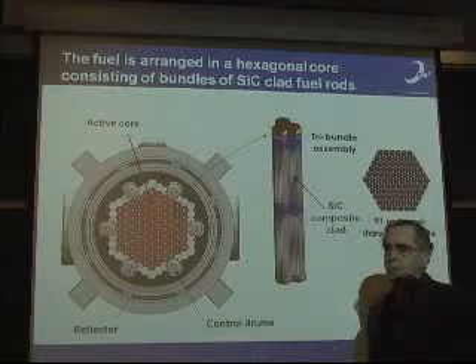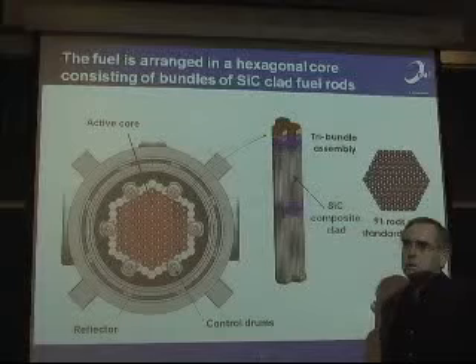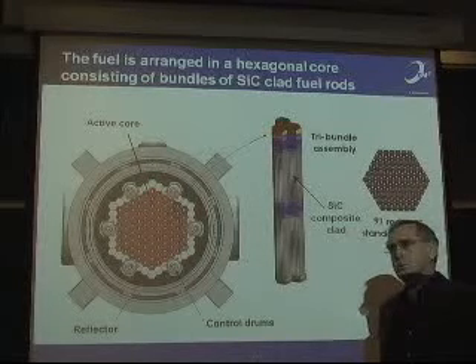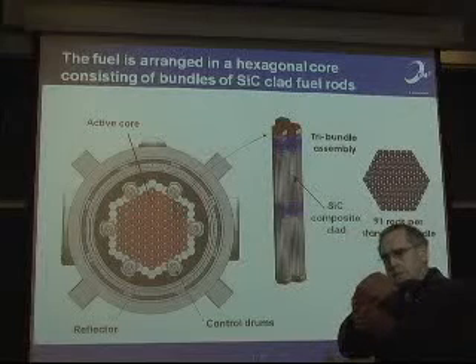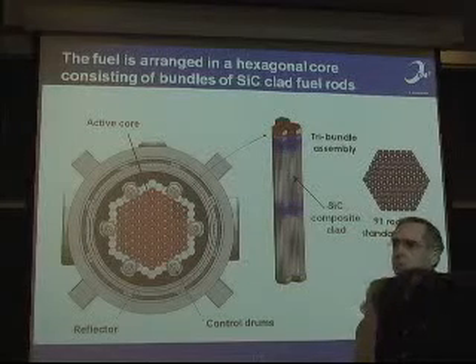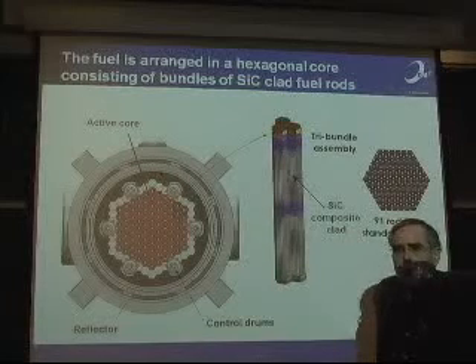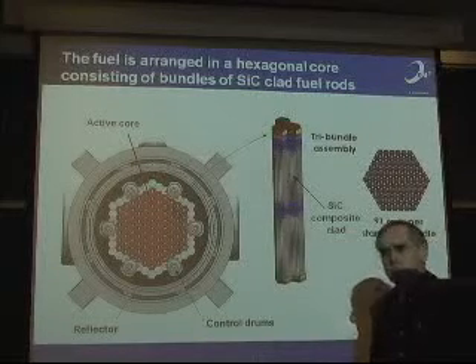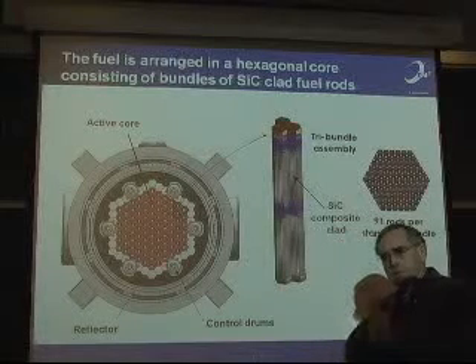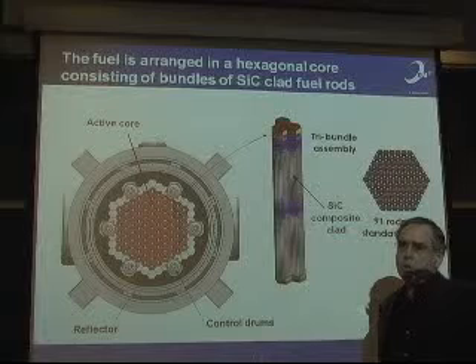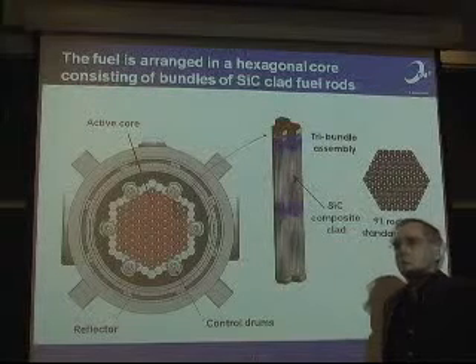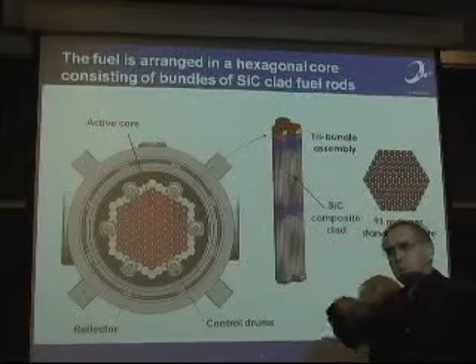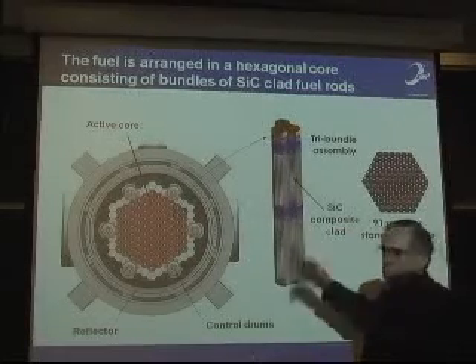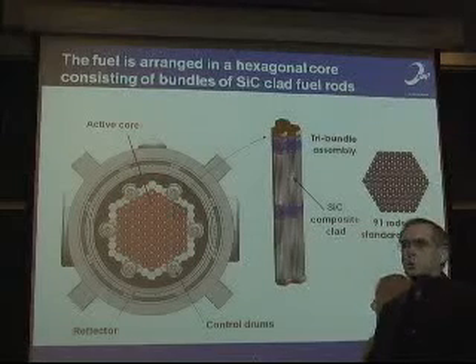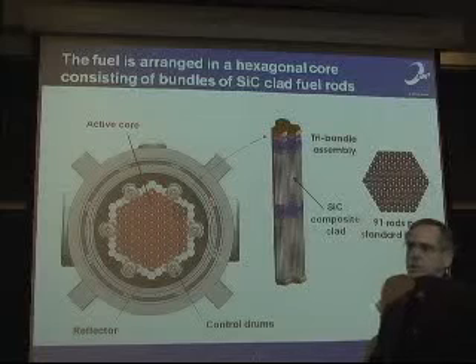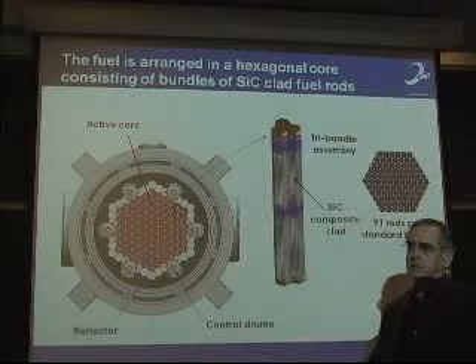Well, we basically proved to ourselves pretty quickly plates will never work because the fuel does swell, and we have to be able to react the swelling of the fuel against the clad so it'll collapse on itself. One nice thing about uranium monocarbide is it has a very high creep rate, and it doesn't take much restraining force to force the uranium carbide to collapse on itself. So we really wanted rods, and we ended up reducing the porosity in order to compensate for the loss of volume by going to rods. And that seemed to work. And so it's a much nicer design overall, and just a much better choice.